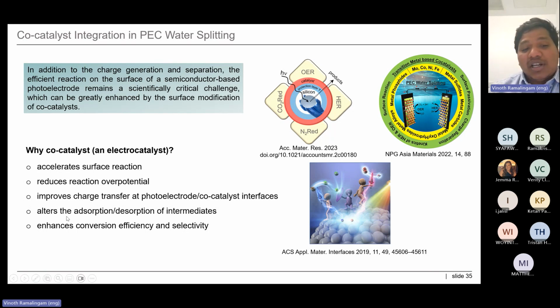And based on the co-catalyst, you can really alter the intermediates to get the specific products that you are looking for. For example, you can use it for water splitting reaction or for other applications. In case of CO2 conversion, you can use a co-catalyst to control the products, for example CO2 to methanol or ethanol or ethylene, you can control what kind of products you want. That can really help you achieve specific products, and it enhances the overall conversion efficiency and the reaction selectivity.